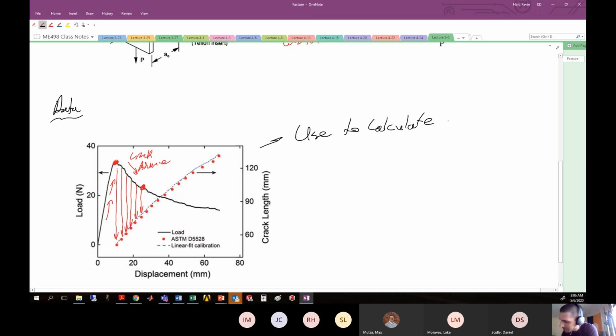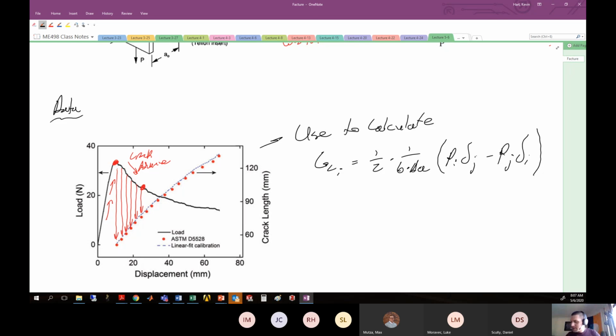the critical fracture toughness of the ith event, which we said was GCI, here equal to 1/2 times 1 on B times delta A multiplied by PI delta J minus PJ delta I. All right, so there's your fracture toughness, your critical strain energy release rate at each individual event. And from there, you can construct the R curve, which plots the crack advance delta AI versus GCI.